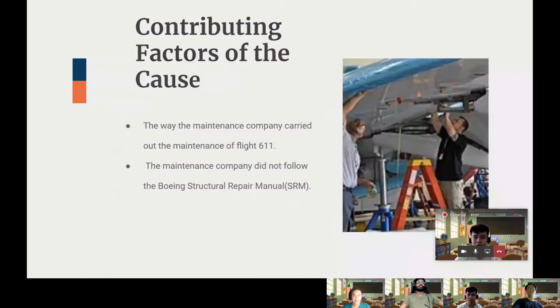Another contributing factor that led to the crash of Flight 611 was the way the maintenance company carried out the maintenance for Flight 611. After the tail strike incident, the permanent repair of the tail strike was supposed to be carried out in accordance with the Boeing Structural Repair Manual, also known as SRM, by the maintenance company. According to the SRM, repairs can be made either by replacing the entire affected skin or by cutting out the damaged portion and installing a reinforcing doubler plate to restore the structural strength. However, the maintenance company from China Airlines did not follow the SRM. Instead, the China Airlines maintenance team carried out the maintenance even though the damage inflicted on the tail was way beyond the damage that a doubler is meant to fix.